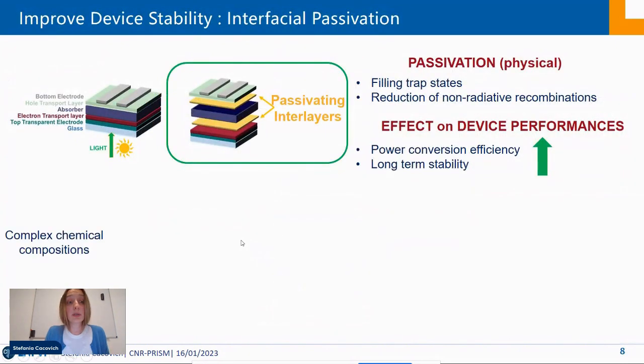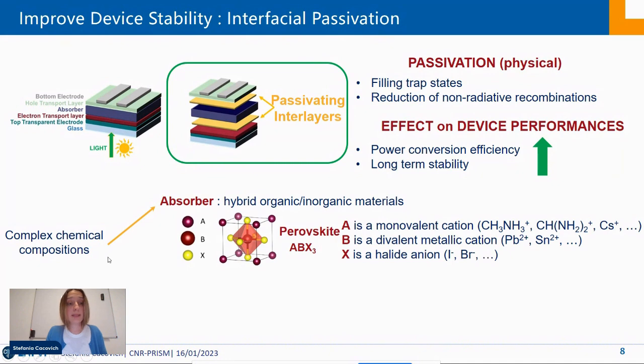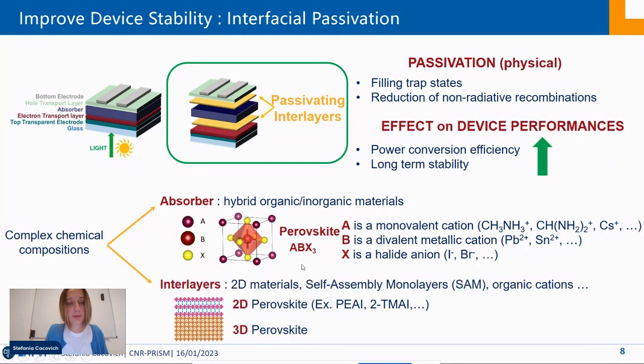However, the system is quite complex because the absorber itself has a complex chemical composition. We are talking about a family of hybrid organic-inorganic materials where this is the chemical structure. So we have a structure ABX3, this is the structure of perovskite, and in the case of halide perovskite, A can be a monovalent cation, such as methylammonium, formamidinium, or also cesium in the case of fully inorganic solar cells. Then we have another metallic cation, and finally a halide anion.